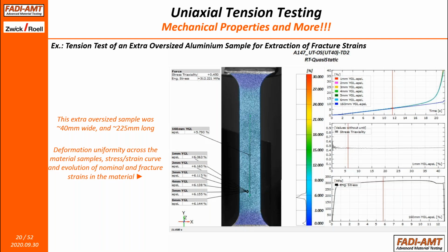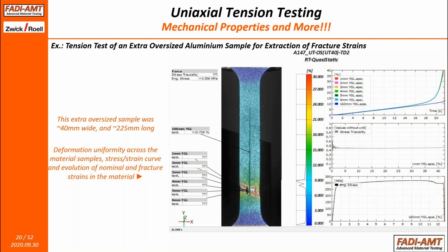So this is one of the larger samples, not necessarily the largest, but the larger samples that are used for the same exact purpose. And you can see here again, there are multiple small virtual extensometers applied to the point of fracture in order to obtain the fracture strains for this 40 millimeter wide sample, which will allow the user to match their mesh size in a finite element setup to around, I would say, 6 millimeters. You could go potentially to 8 millimeters with this kind of a setup.